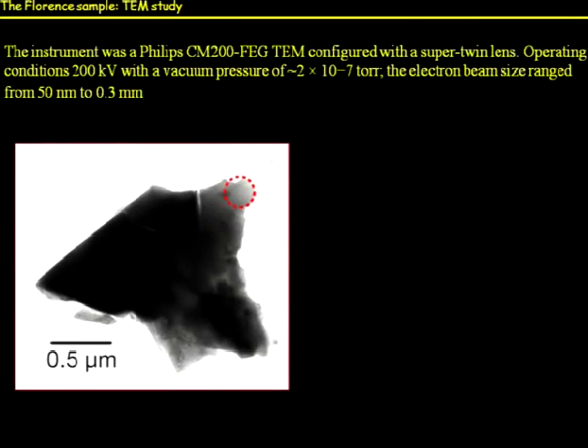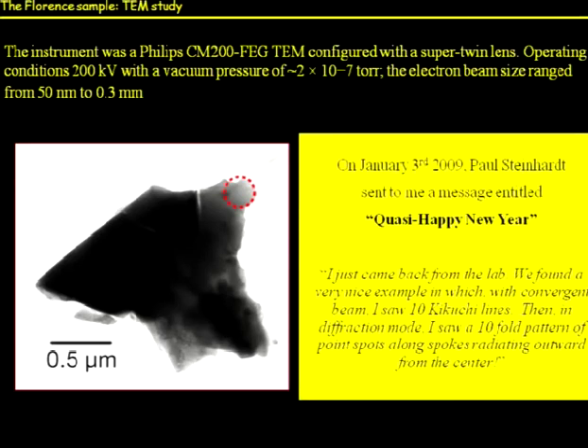So when Nan took one of these and put it in acetone, the grain dissolved into several micrograins. He was able to select one of these grains, 1 micron in size, and this grain showed thin edges able to give an electron diffraction pattern. Well, it was the beginning of 2009 when Paul sent me this email, "Quasi Happy New Year."